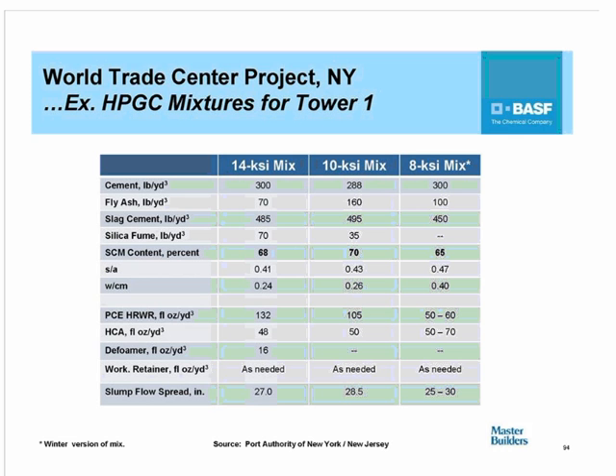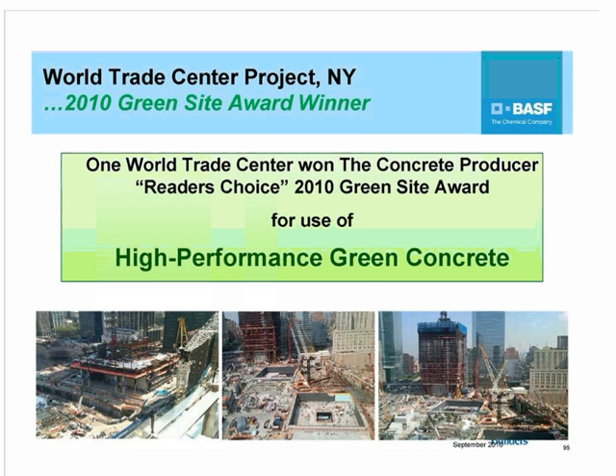But the system of admixtures that were used essentially allowed the concrete to be pumped all the way up 90 stories without any problems, and for the strength to be developed without too much issue. And as a result of that, the One World Trade Center actually won the Concrete Producer Reader's Choice Award in 2010 for the use of high-performance green concrete. This was as green as you could get the concrete to be.